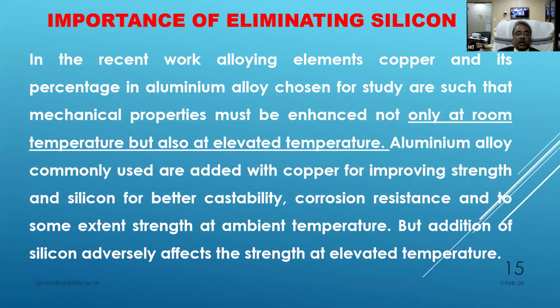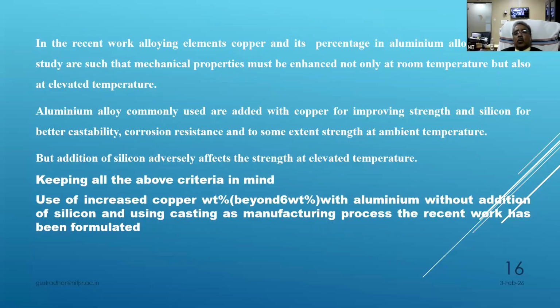But the addition of silicon adversely affects after some point. So if it is under some elevated temperature, that is 250 and above, then silicon addition should be restricted. So in this work, I will show you increased copper weight beyond 6% with aluminum, without addition of any silicon, using casting as the manufacturing route. The recent work has been formulated this way.